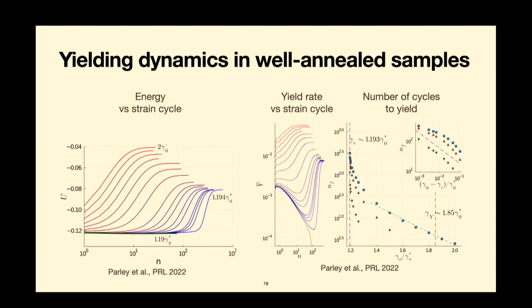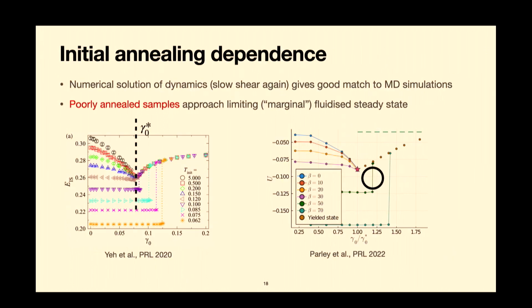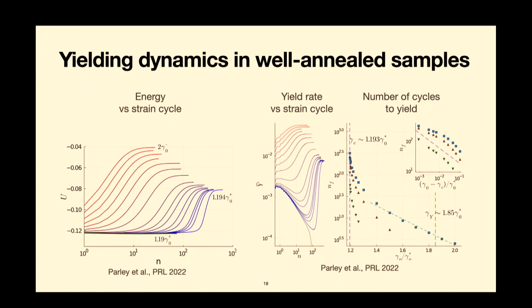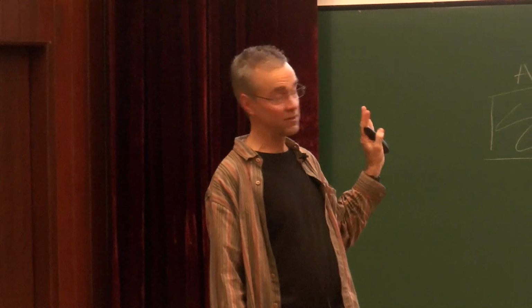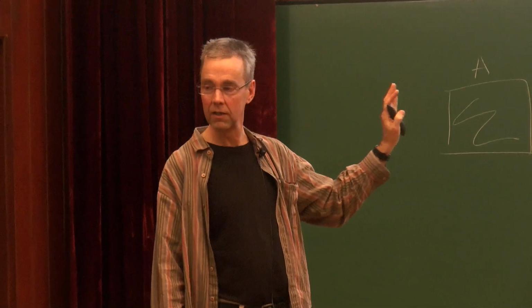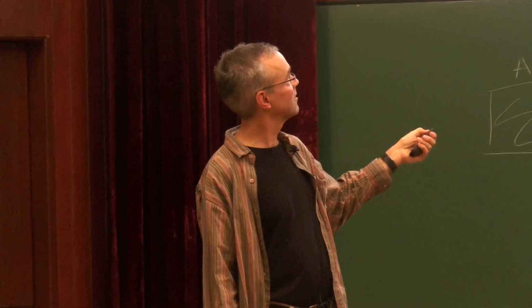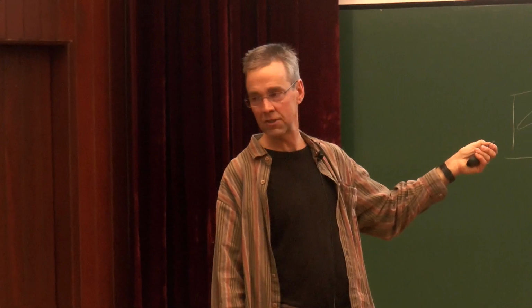Of course, if you're very close to this point, not near the star but on the other side, so if you're basically where the circle is, but just to the left, then of course you see the remnants of this kind of critical transition. You see that the relaxation there is a power law, whereas if you go to lower strains, then it's faster. So yes, you do see a signature: as you go beyond gamma star, the way the system reaches its steady state becomes slower and slower, eventually becoming a power law.